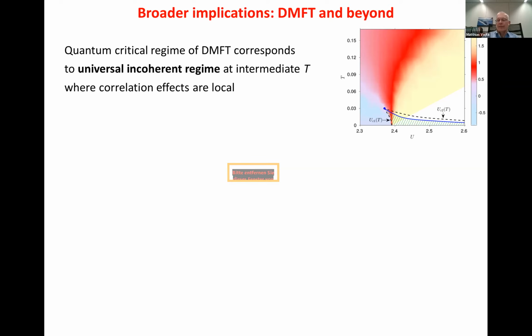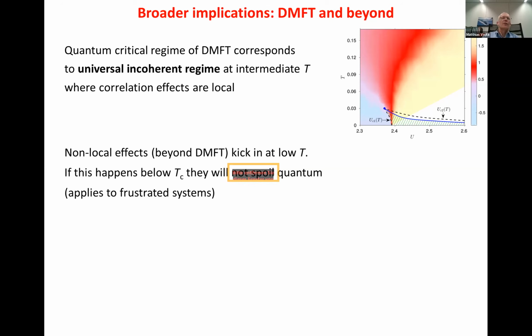This is where this quantum critical scaling appears, and apparently, as described by DMFT, the correlation effects are fully local. Now, if you go beyond DMFT, non-local effects would become important at low temperatures. But it's plausible that if this happens only at temperatures below the temperature of the critical endpoint, Tc, then this quantum critical scaling, mainly observed up here, is not influenced.